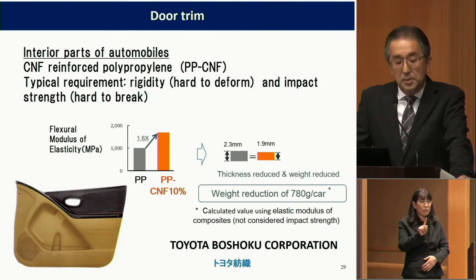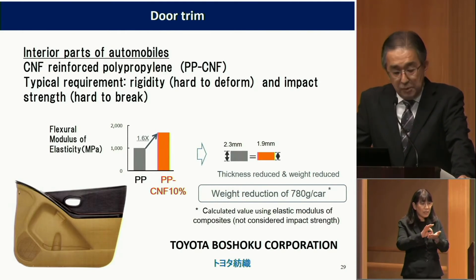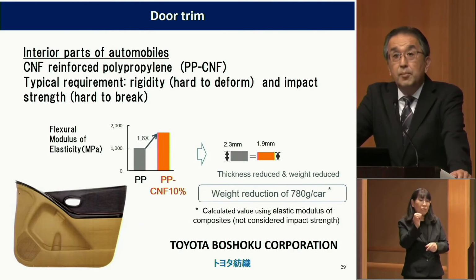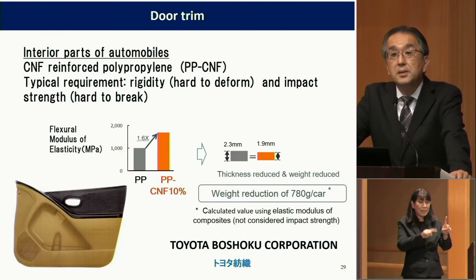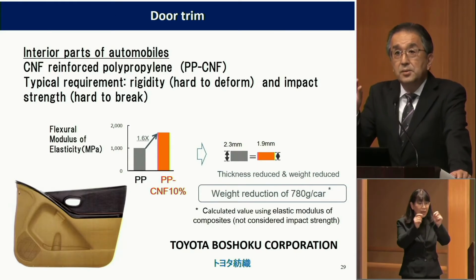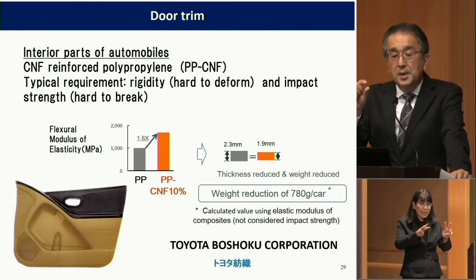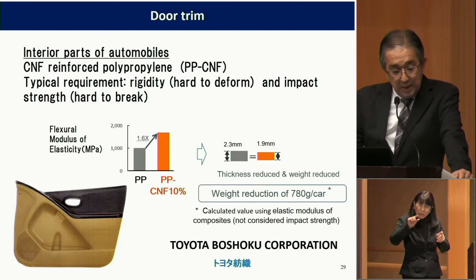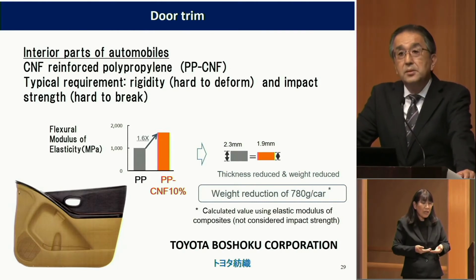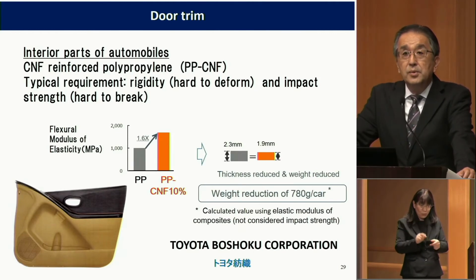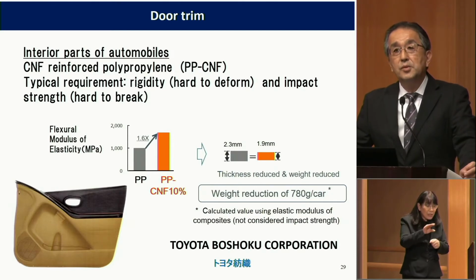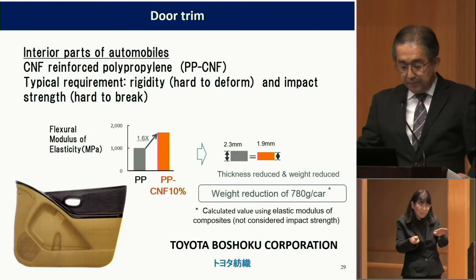This is the polypropylene CNF composite door trim. That's a prototype of door trim. So adding 10% of CNF to polypropylene increases the modulus by 1.6 times. As a result of that, the board thickness was changed from 2.3 millimeters to 1.9 millimeters. Then the total weight was reduced about 10%. This door trim was manufactured by Toyota Boshoku, and this door trim was installed on the final prototype car.